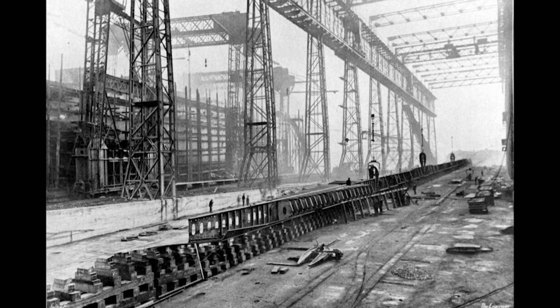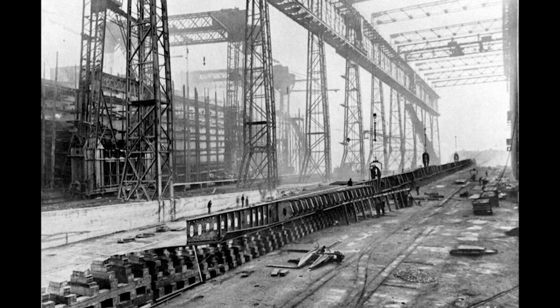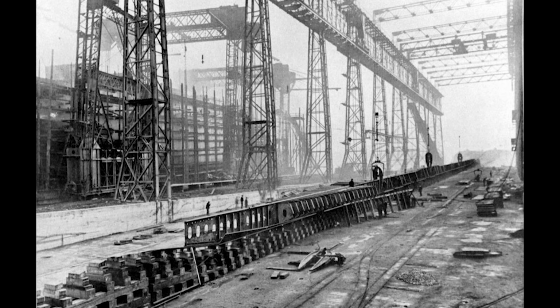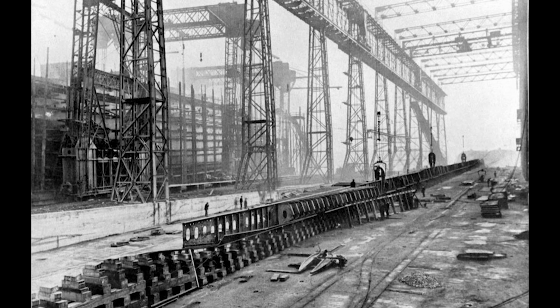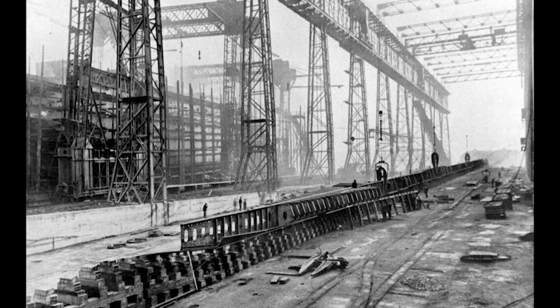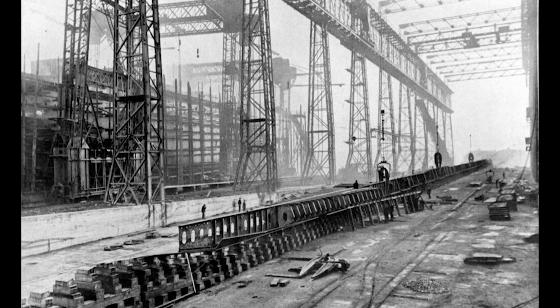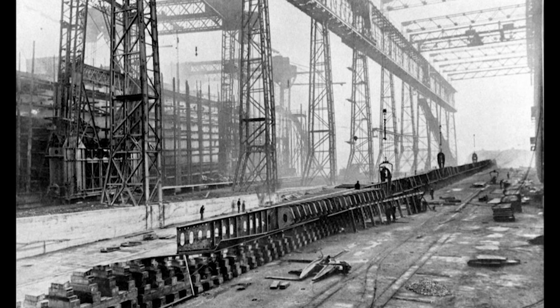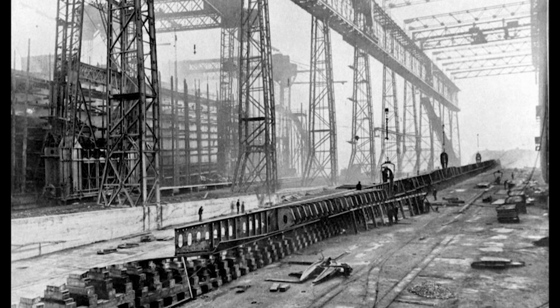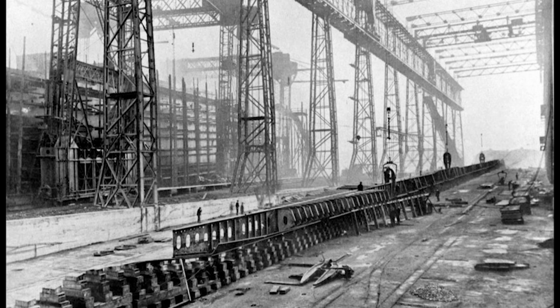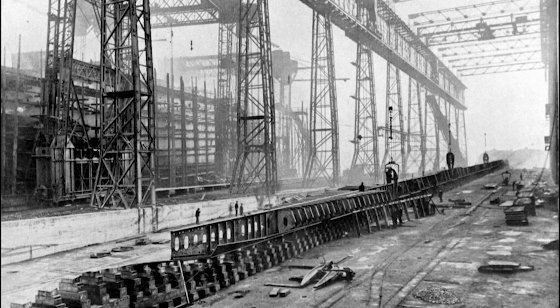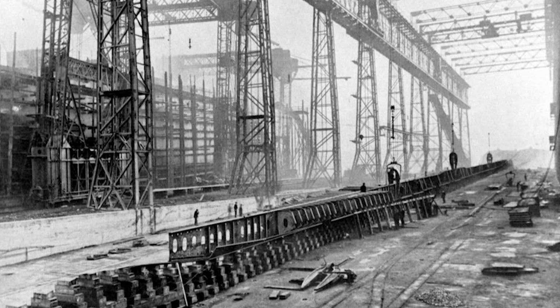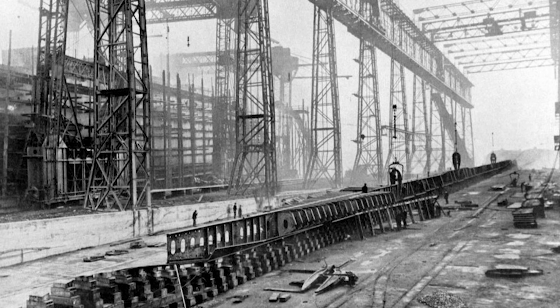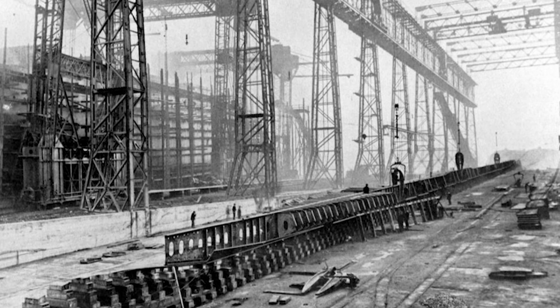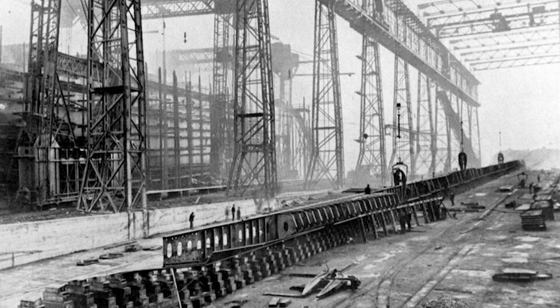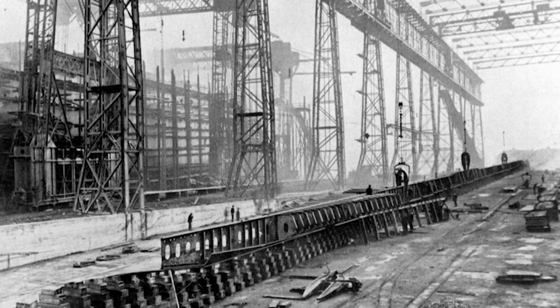At room temperature, steel samples from Liberty ships exhibited excellent ductility, bending and deforming gradually under increasing stress loads. But when identical steel specimens were cooled to 40 degrees Fahrenheit, the temperature of North Atlantic and North Pacific waters during winter months, the same material became brittle as glass, fracturing suddenly and completely under loads that would normally cause gradual yielding. The ductile to brittle transition temperature represented a fundamental property of steel composition that determined whether structures would bend or shatter under identical stress conditions. The mathematical precision of the temperature effect astounded even Tipper, whose theoretical work had predicted similar phenomena without access to failed structural samples for verification.